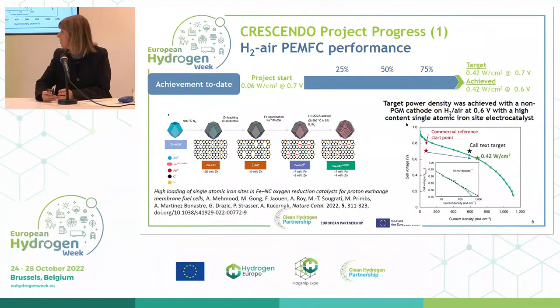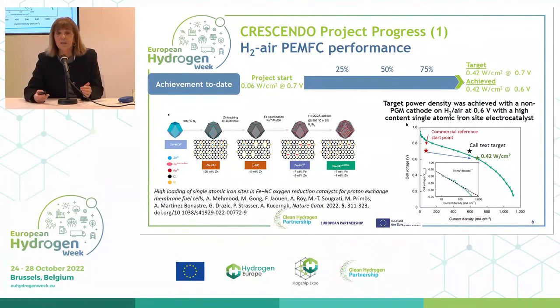So the approach that we used here, which is given on that left-hand side of the screen that I'm not going to go through in any detail, is an approach that allowed us at the end to largely increase, in fact, the active site density. The state of the art generally is for a material containing around 3% weight of iron. That catalyst there contains 7% weight of iron. It's quite common in these catalysts that there's also the co-production of inactive species, which might be carbides, for example. But this is a highly dispersed iron catalyst. We term it a single atom catalyst in the sense that the iron is very highly dispersed throughout that microporous support. And you can see that it also gave rise to a very nice publication in Nature Catalysis.